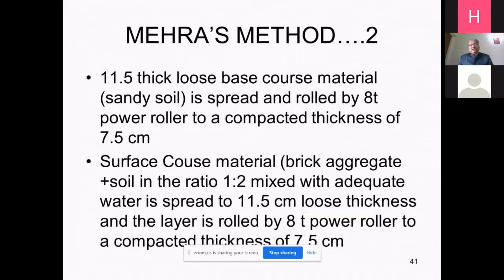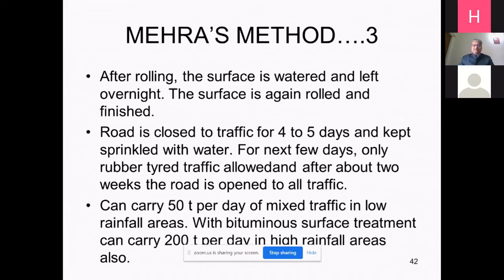And in this, the loose thickness is 11.5 centimeter, which is rolled and compacted to a thickness of 7.5 centimeter for the base course. Similarly, for the surface course also you have the 11.5 centimeter loose thickness, and it is rolled by an 8-ton power roller to a compacted thickness of 7.5 centimeter. After rolling, the surface is watered and left overnight. The surface is again rolled and finished. So the road is closed to traffic for 4 to 5 days, and it can carry 50 tons per day of mixed traffic.